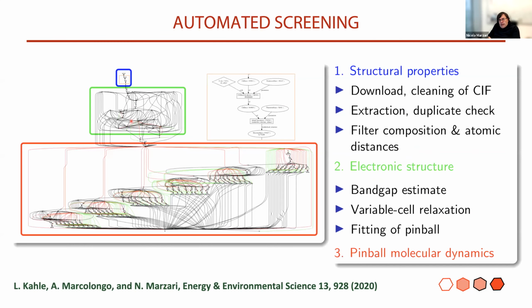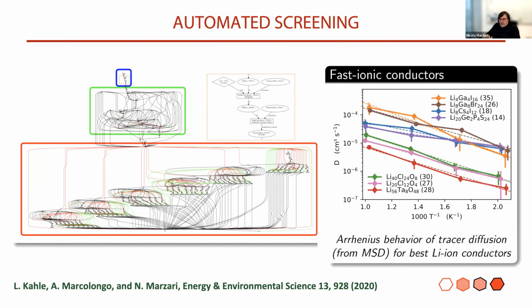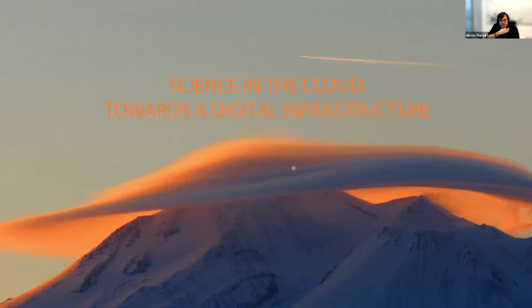So basically, we look for every material that contains lithium in our inorganic database. We automatically fit either a physics-based model or a machine-learned force field, and out of that, we calculate from molecular dynamics at different temperature, the diffusion coefficients, and the activation barrier. And again, this is very much work in progress. And again, one of the nice things is that these days, this work is completely funded by industry. That just means that it's relevant enough for them to invest.